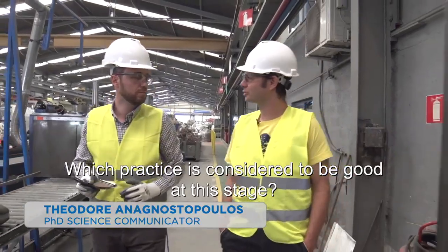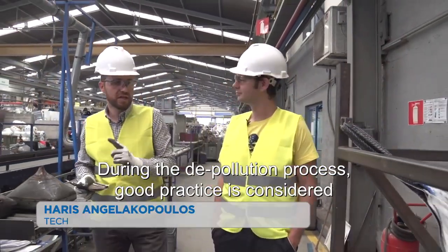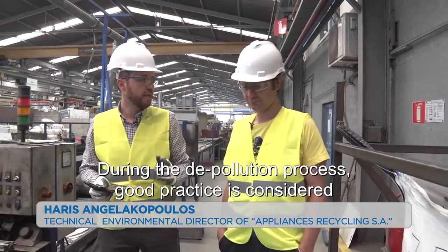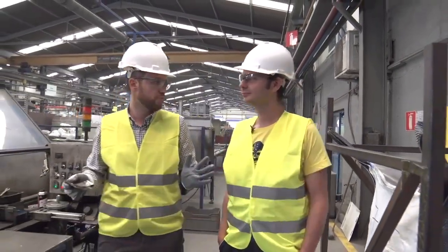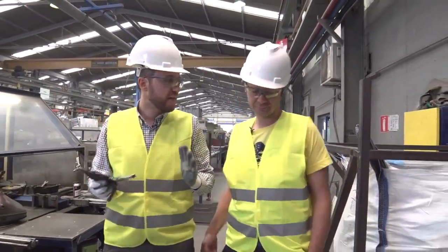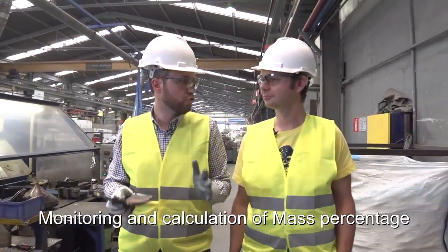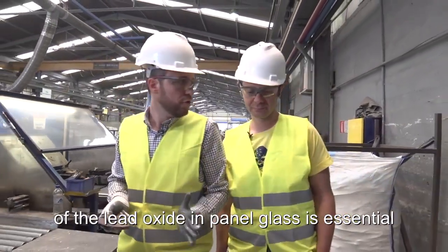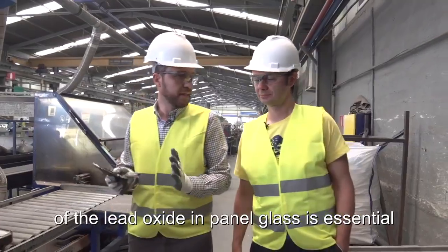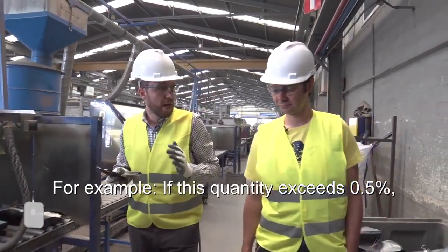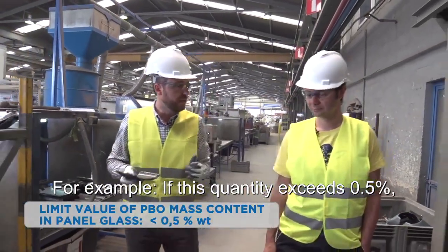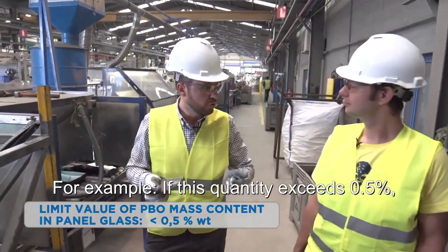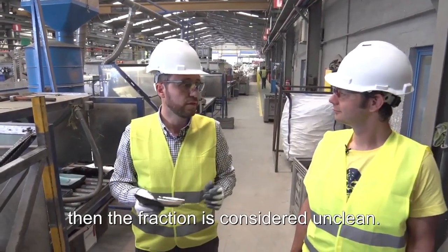Which practice is considered to be good at this stage? During the depollution process, good practice is considered the optimal splitting of the two glasses. Monitoring and calculation of mass percentage of the lead oxide in panel glass is essential. For example, if this quantity exceeds 0.5%, then the fraction is considered unclean.